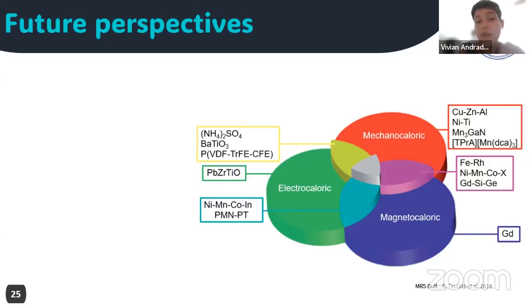In the alloy, in the gadolinium silicon germanium case, for instance, you have the 3+ gadolinium. But what's interesting is that you don't have the magnetism in gadolinium silicon germanium only from gadolinium, because you have the hybridization between the silicon and germanium contact that increases the magnetic moment of the material. It's because of the construction of the structure. You have like blocks of gadolinium, silicon germanium connected with covalent bonds of silicon germanium.